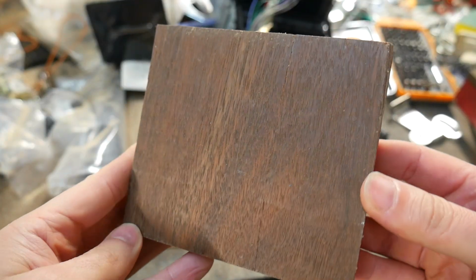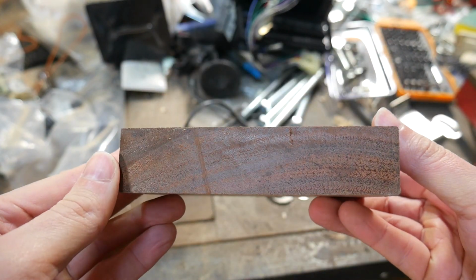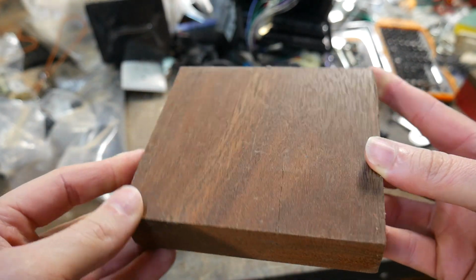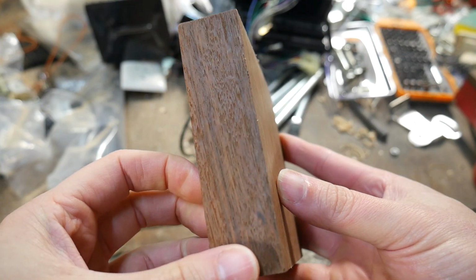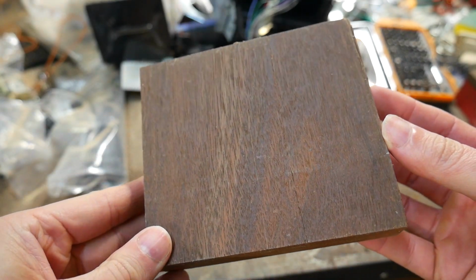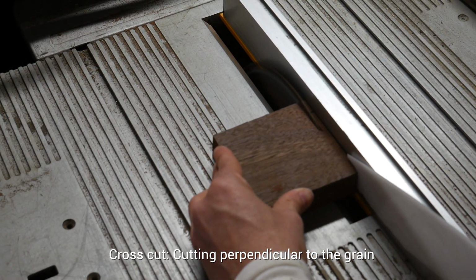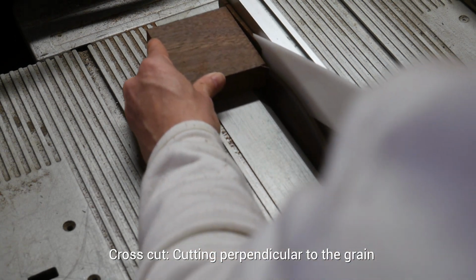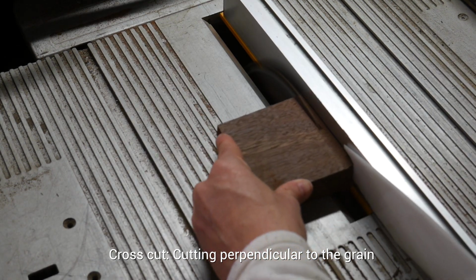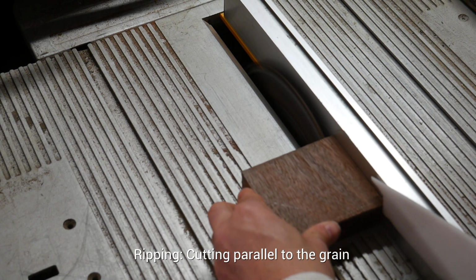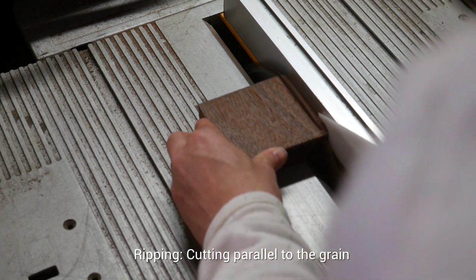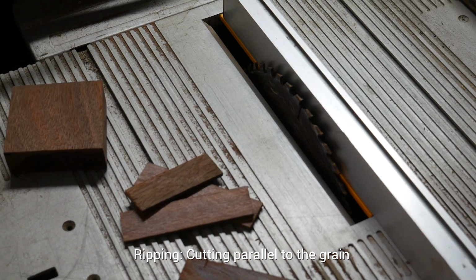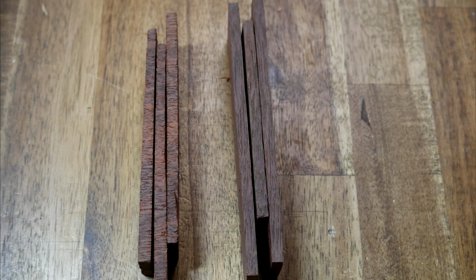So here we have a piece of Australian hardwood called Jarrah, which is known not only for its looks, but also for being very dense and very tough, ideal for furniture making. And what I did was take a table saw and take a series of slices off this single piece, with half of them being cross-cut, that means cutting across the grain, and the other half being ripped, which means cutting in the same direction as the grain. That gives us some samples for destructive testing with a clear distinction.